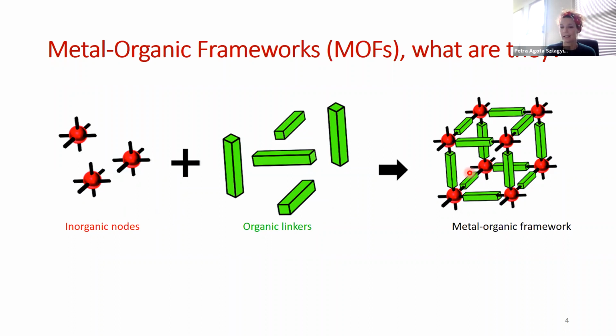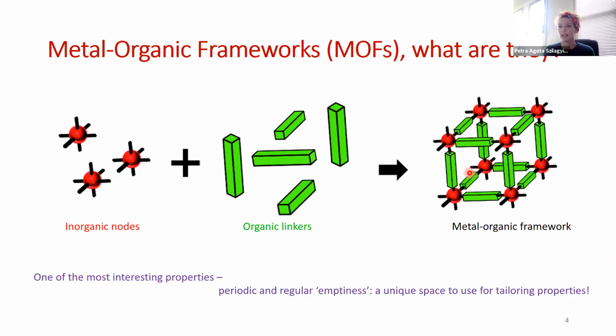And this is really where my interest lies, because it should be pointed out that the pores themselves are part of the crystal structure. And as such, their size and shape is very well determined, on the atomistic scale, really. So in a sense, we get these bits of emptiness, these pore spaces, which for catalysis we mostly exploit as a kind of mold for growing catalyst nanoparticles and nanoclusters inside. And so we get to engineer the size and the shape of these particles very closely.